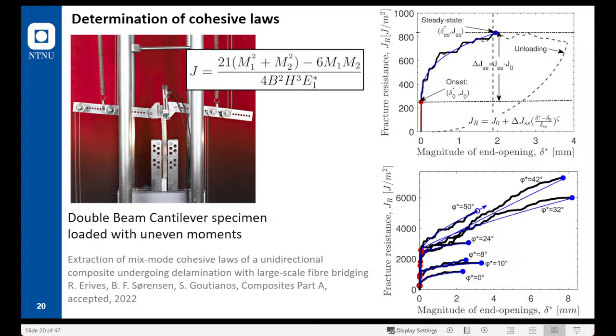I'll go now to the experimental details. We have to develop techniques so that we can accurately measure the cohesive laws. This is a photograph from my colleague who developed this technique. This is our composite material, you can see here, and we apply the load through these moment arms. By changing the moment arm, keeping the force constant, we can change the moment, and in this way we can test any kind of mode mixity, from normal to shear opening, and also all the phase angles in between.